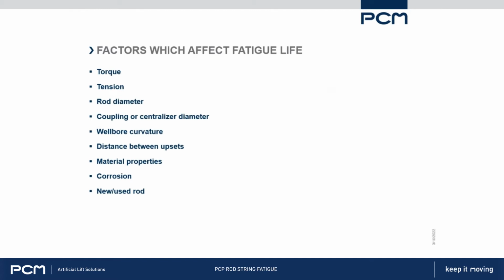New rods shouldn't have any fatigue cracks in them. Used rods, whatever cracks were there from the previous installation are still there. And if that rod goes back into the same place or somewhere in the well where it's even higher bending stresses, then it's going to fail very soon, because the cycle count doesn't reset to 0 just because you did a workover. It continues from where it left off. On the bright side, often the rods don't go back in the same place. So if you have a rod that had some significant fatigue cracks, if that rod happens to be placed in a straight section of the well on the second run, maybe you get some better life out of it, but you can't guarantee that, of course. So we'll talk more about that in a minute.